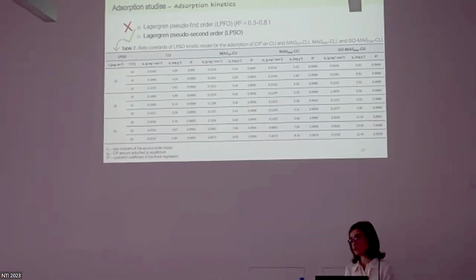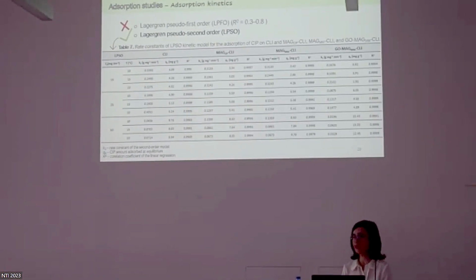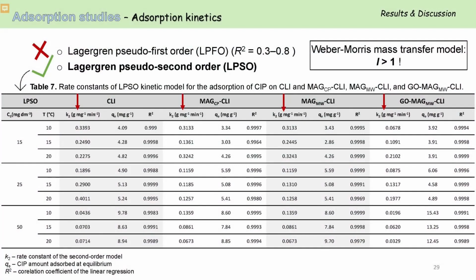The adsorption kinetic data obtained were then analyzed by 2 kinetic models, the Lagergren pseudo first order and pseudo second order. The pseudo second order shows significantly better fits according to the linear correlation coefficients. So this is the reason why I will put these results here. And the rate constants change rather irregularly with temperature for all studied adsorbents. This phenomenon was also observed for ciprofloxacin adsorption on mineral clay and aluminum oxide, which indicates the complexity of the ciprofloxacin adsorption mechanism.